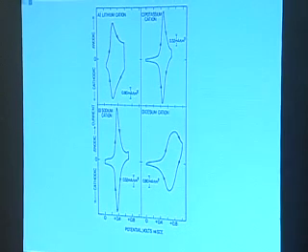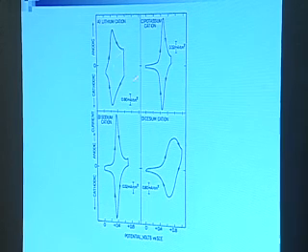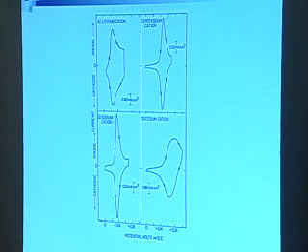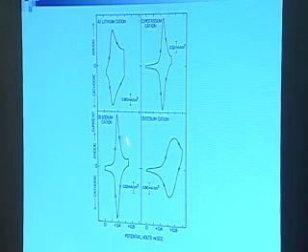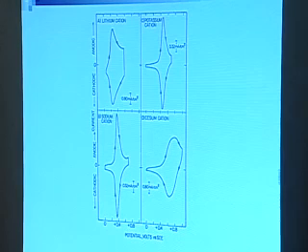This was the last topic we started to get into last hour, and that is, if we take one electrode with nickel ferricyanide on the surface, and we put it in a variety of electrolytes with the same anion, nitrate in this case, but different cations using the alkali cations, we get a very different response. And we spent a lot of time studying this. It has lots of implications. The first thing you notice about this response is as you go down the periodic table here, the peak half-wave potential is shifting. And it's just more positive going from lithium to cesium.